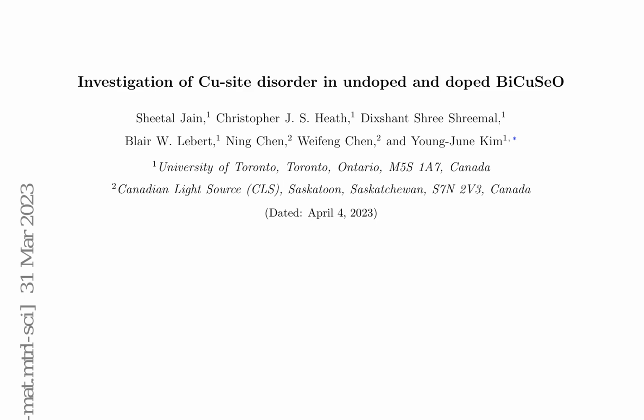The observed data is shown in red, while the calculated fit is the solid black line. The fit is seen to match the data well, yielding Rwp equals 5.33% and chi-squared equals 2.19. These goodness of fit parameters are found to be similar in value for fits at all temperatures. The difference profile is shown in blue and is found to be within the measurement uncertainty throughout the entire range. The expected XRD peak positions for BiCuSeO, based on the crystal structure in Figure 1, are shown via the green vertical lines.